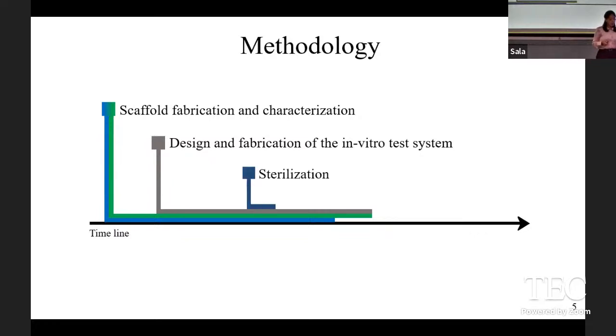Going forward, we also did the sterilization procedure considering all the things that I mentioned before. So for instance, we needed to use a sterilization procedure that was proper for biopolymers. We couldn't use any high temperature sterilization procedure, and also a sterilization that was proper for the in vitro test system. For sterilization, we did two types of tests. One was the pathogen estimation on the scaffolds, and the other one was the dose distribution in a sample chamber, because we chose to use 25 kilograys of gamma rays for sterilization, and therefore we wanted to see the dose distribution.